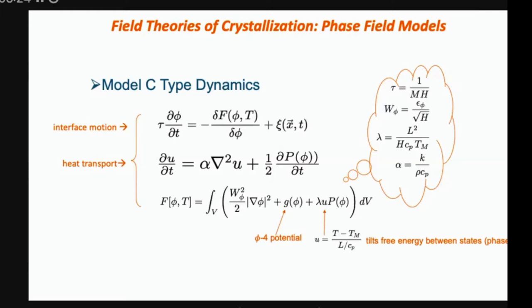And this free energy is very well recognized in the physics community, a kind of Ginzburg-Landau free energy, and instead of making mu a constant, we make it a field, that's when you get two equations. And one term sort of creates two states of phase or phases of this system, solid liquid. And the last term in the equation in the free energy represents a kind of bias or breaking of symmetry between the two states, saying, well, the hotter state is more stable or less stable, depending if you're above or below an equilibrium. And T here represents temperature.